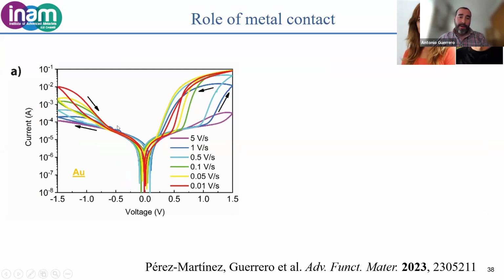So these devices, because we are moving ions inside. This is with gold, non-reactive perovskite and gold, no buffer layers. The ions move inside the perovskite, and then depending on how fast I'm sweeping the voltage, the hysteresis totally changes. This is because when we go very fast, the ions cannot follow the electrical field, because the electrical field sweep is very fast, and the ions don't move so fast.